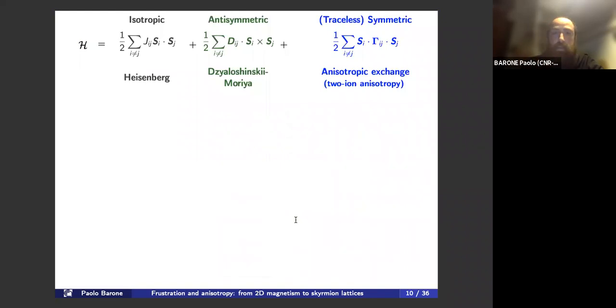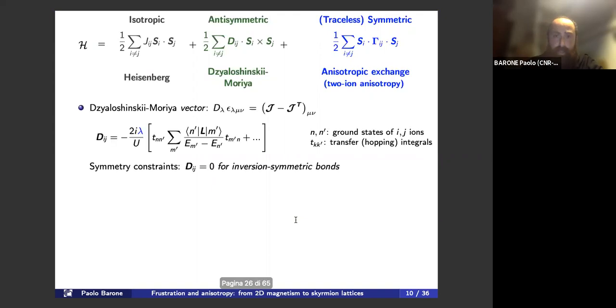Now, let's have a more detailed look at these new terms. The Dzyaloshinskii-Moriya interaction can also be derived as part of the Anderson superexchange, like the Heisenberg interaction. The difference is that instead of having just one virtual intermediate state, where one electron jumps from one side to the other with opposite spin and then jumps back, we have the possibility of a mixing, mediated by the spin-orbit coupling, between the states of one of the two sites.